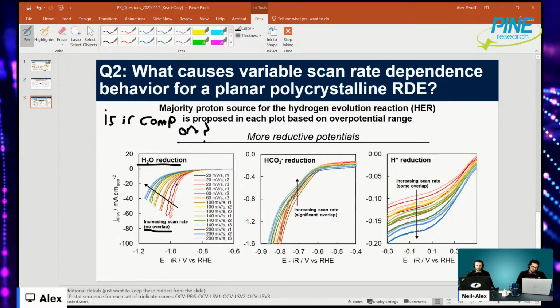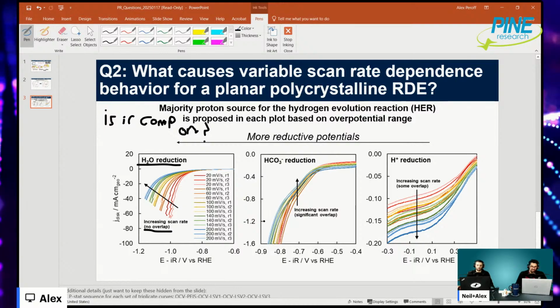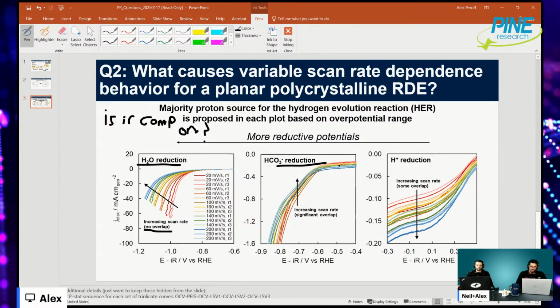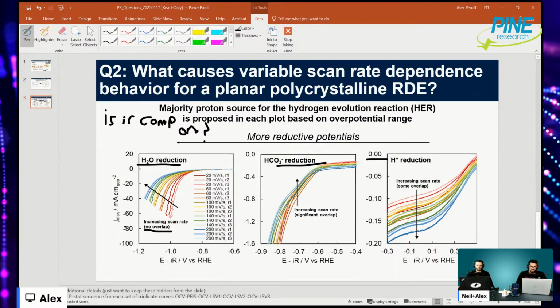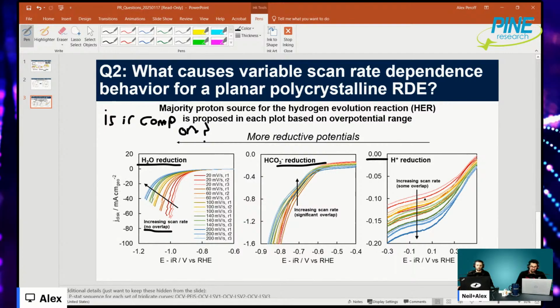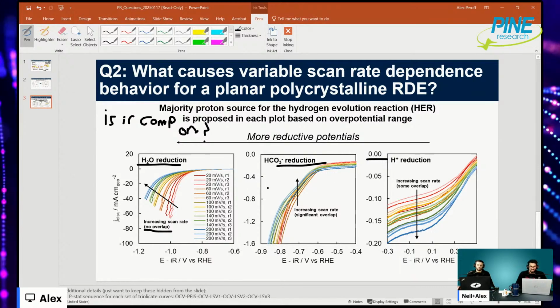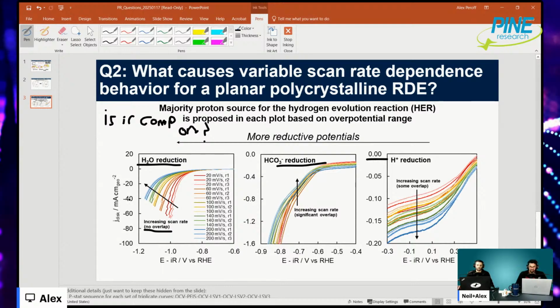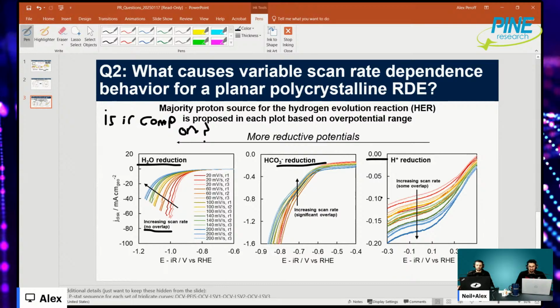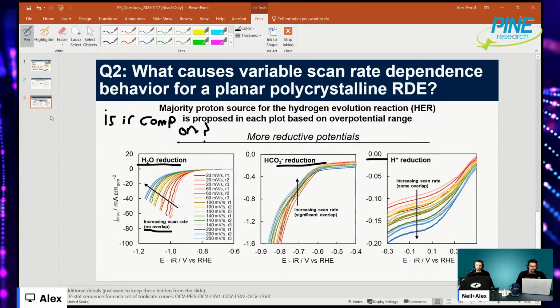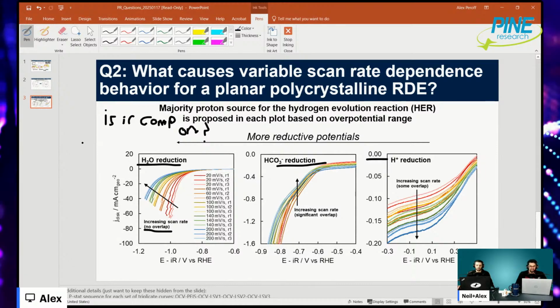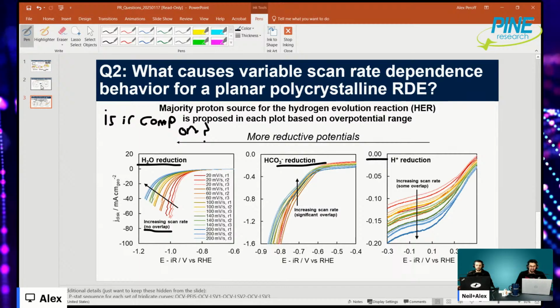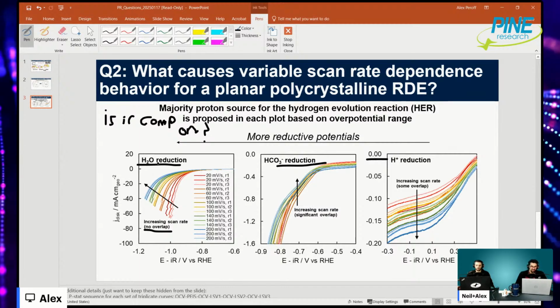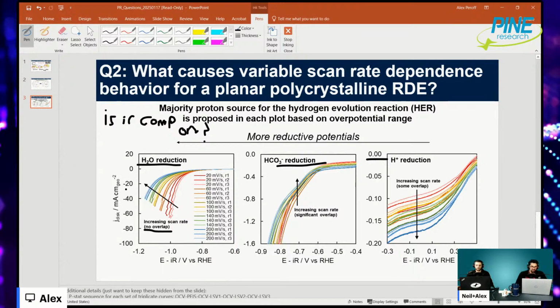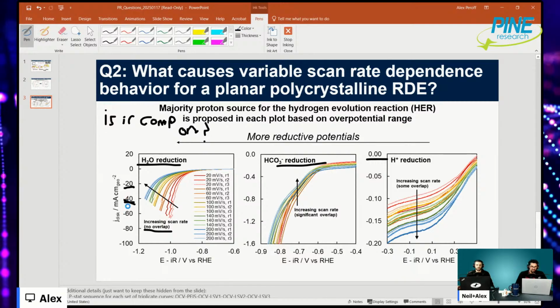If we look at this, the y-axis scales are fairly different between these three. So for H plus, we got 0.05. I'm assuming these are the same units, milliamps per square centimeter. This is 0.05 milliamps per square centimeter. This is 0.4 to 0.8 milliamps per square centimeter. And here we have 20 and 40 milliamps per square centimeter. We have huge differences in the magnitude of the current. So when you mentioned earlier that you're actually seeing huge deviations in the solution resistance changing your results, that will be in big part due to how large the current is.